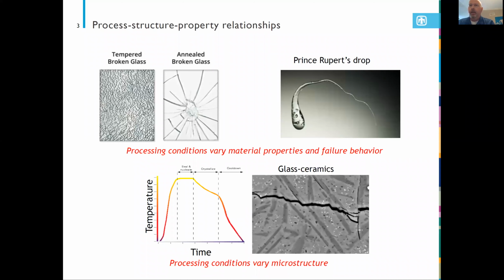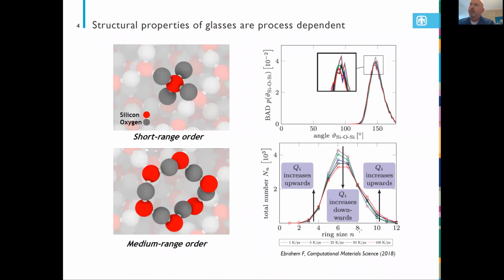And then if we start to talk about the atomistic scale, what exactly is going on in terms of these process structure relationships, it's important to note that when people typically think about a glass, they think of something that's completely amorphous, lacking structure, and that's not necessarily the case. Silica-based glasses, which are primarily about 60 to 70% silicon and oxygen, typically have short and medium range order.